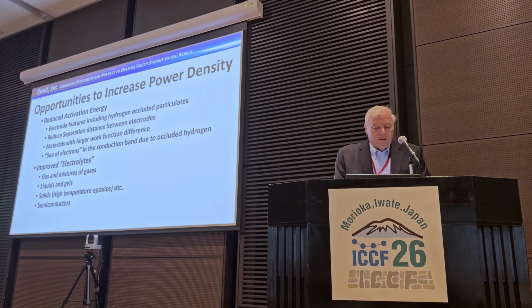Improved electrolytes. We've talked about gases. We've talked about hydrogen, but we also are looking at pinning gases. We've tried a mixture of hydrogen and argon. We think maybe hydrogen and propane might be a good pinning gas. You know, you get a bigger molecule, you may knock off more electrons. So that's the central theory there. Liquids and gels, we've tested these. The big concern there is we want to be sure we aren't creating a Volta effect, which is an electrochemical effect. Solids and high temperature epoxies.